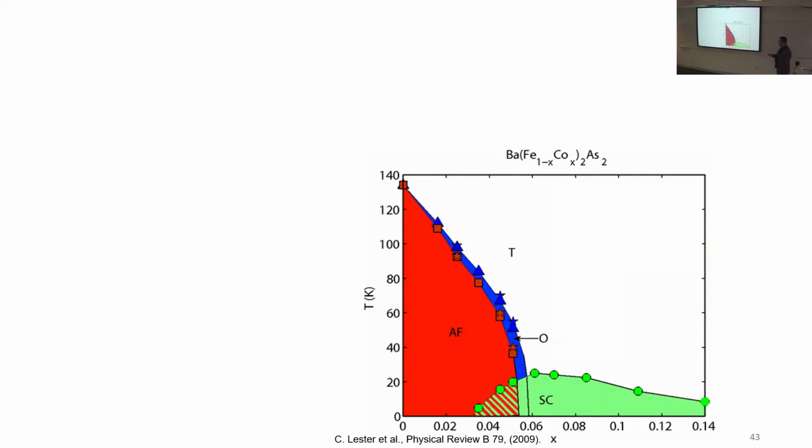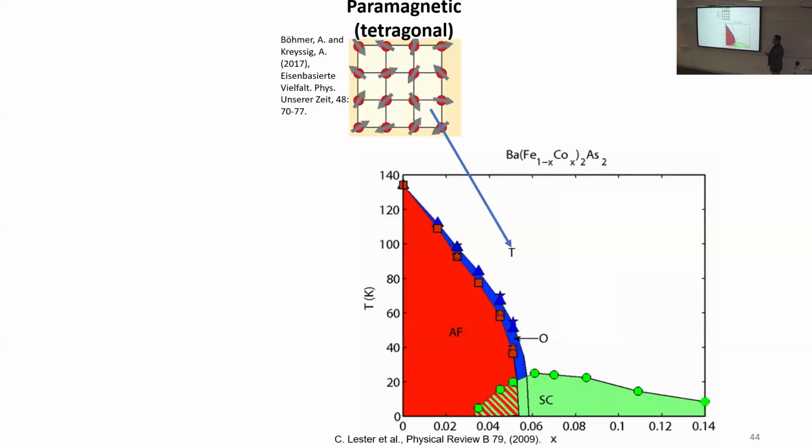dope these materials is clear from this phase diagram. The more you dope it, that's where the superconducting dome appears, and so that's why this is done this way. There are three phases that I'd like to talk about, though, which are general to these materials. The first one is being covered by the green. It says paramagnetic up there. The first phase, which is the high temperature phase, is the paramagnetic phase. It is this phase which is tetragonal, meaning that the sides of the lattice are equal to each other. In this phase, there's no magnetic ordering.